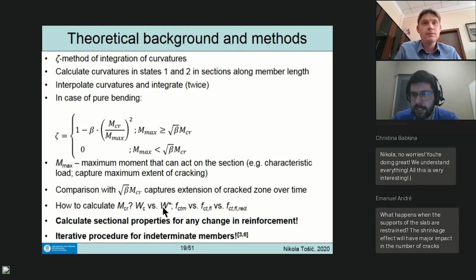Naturally, what you would associate with bending would be the flexural tensile strength. That somehow seems intuitively natural — with which strength does concrete resist flexure if not its flexural tensile strength? But because these models contain some empiricism, for example this ζ-method, they are also calibrated on some databases of results. And it seems that, when they were formulated, they were calibrated to give the best results when you plug into the cracking moment the gross section modulus and the axial tensile strength, the mean axial tensile strength.